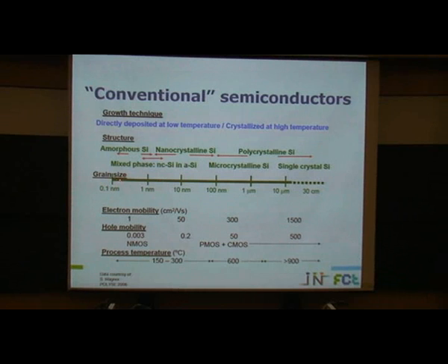For example, if we want to reach high mobility, of course, we should increase the grain size until the monocrystal. And of course, to achieve this, look at the temperatures. The temperature associated is also high. So if I'm using silicon or a conventional covalent semiconductor, in order to have a high mobility, of course, I should increase the grain, and also the temperature associated should be higher.